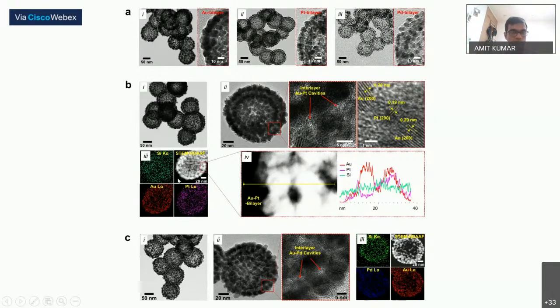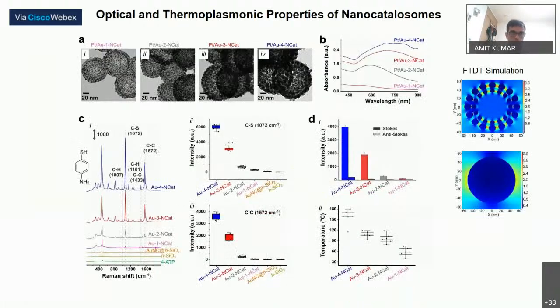So the size of plasmonic nanoparticles modified within can be well controllable, and the optical absorption correlates with the size of these nanostructures. And we also verified the position of plasmonic hotspots by SERS spectroscopy, surface enhanced Raman scattering. So we modify this Raman reporter into the bilayer space with the efficient gold sulfur chemistry, and found that in the bilayer the gold units are very closely spaced and larger in size, such kind of structure shows the highest intensity of the Raman signals.